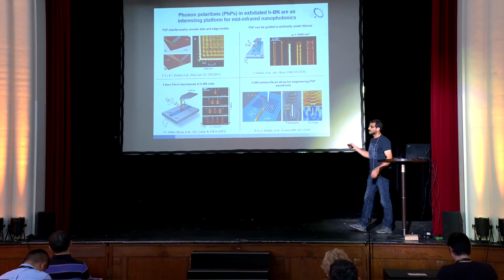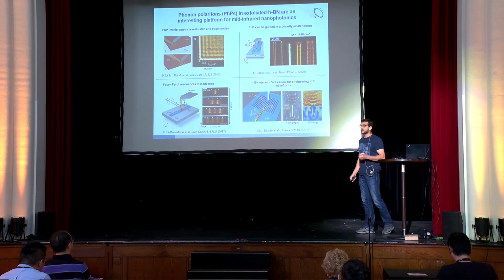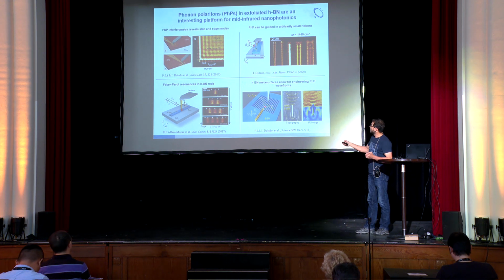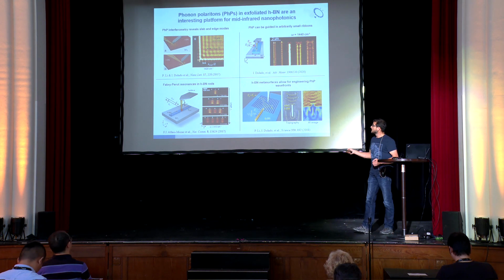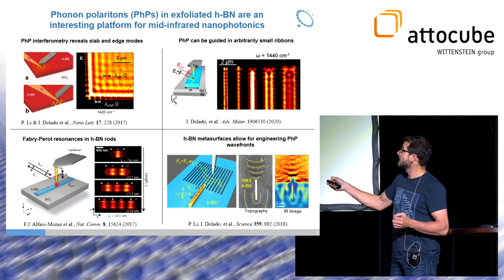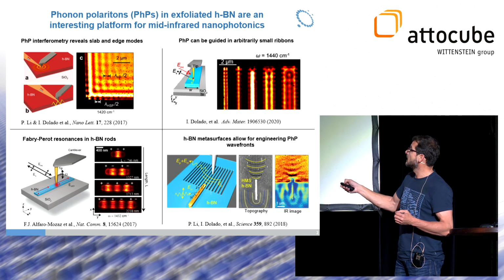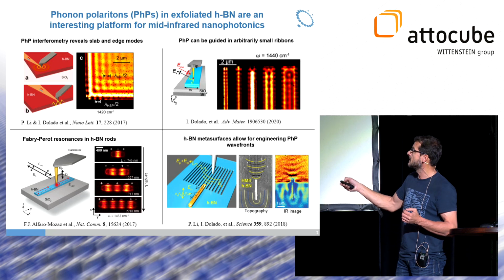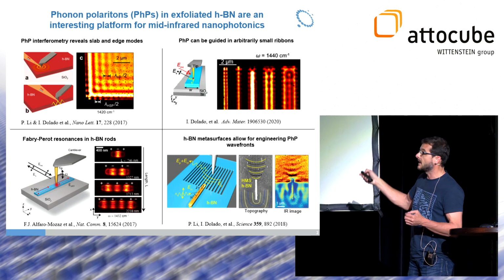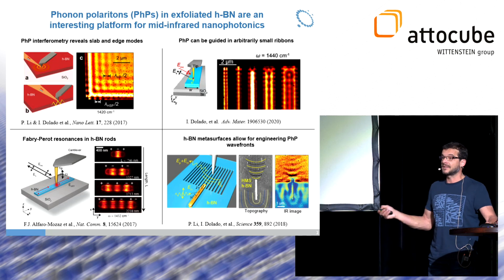And another thing is, what we did some while ago, we can use this, in principle, in-plane isotropic hBN when we can structure it, and then we can make artificial hyperbolic metasurfaces out of that. So what you see here is an antenna on top of a grating, and that launches waves. And as you can see, these waves have tilted wavefronts, the same way as what you see in molybdenum trioxide. The difference is here we break the in-plane symmetry by structuring that. And so now we have an effective epsilon, or permittivity, that is different here than here. And so we can make hyperbolic metasurfaces artificially.